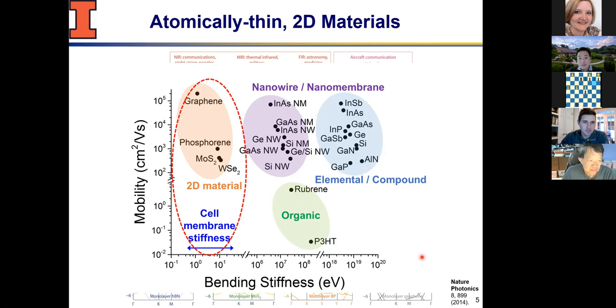And on my x-axis, this is the 2D bending stiffness, where you can see that this number varies drastically as a function of the thickness of the material or the dimension that we're looking at. For example, in the nanowire or nanomembrane, that's either the diameter or the thickness of the membrane, say 100 nanometers, or there are some variations, so we would use these areas to show that. Organic semiconductor sits in here. That's also, again, a function of the thickness of the material. Of course, bulk will be way, way far on the right-hand side. But when you get to a very thin thickness of the material, you start to realize this number reduces drastically. It's simply a thickness effect and the stability of the material at that particular thickness. And if you put in some of the biological systems when it comes to bending, they start to be comparable. So it's quite interesting just to see this chart.